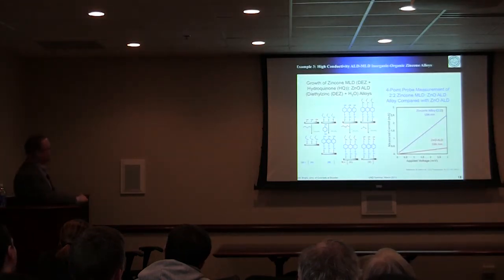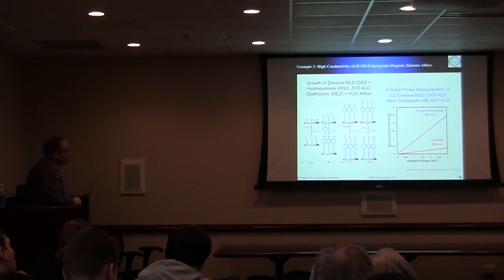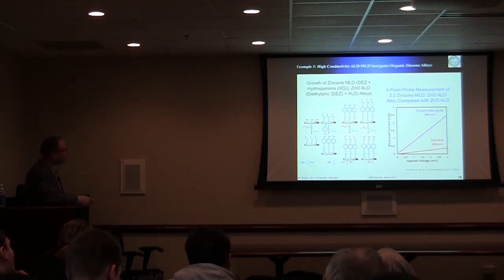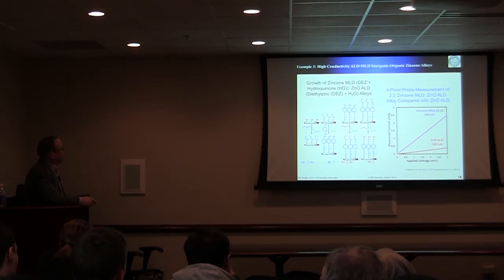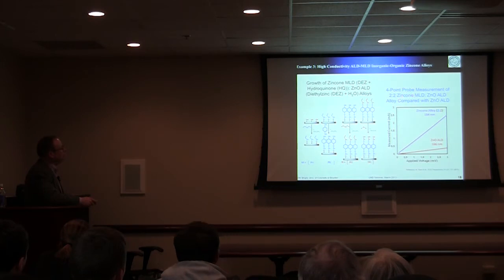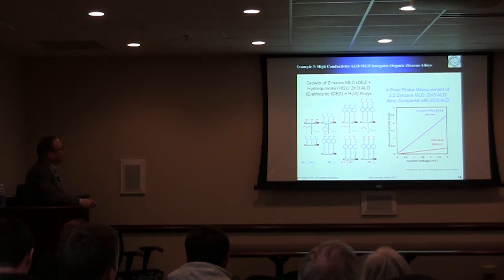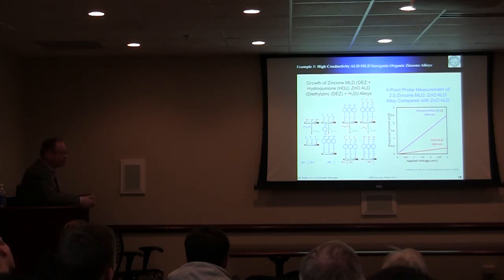And so, speaking of transparent interconnects, more recent work from CU Boulder would be zinc oxide or zinc-based MLD based on diethyl zinc. And with this type of material, instead of alucone, we could produce something called zincone. But once you mix zincone with zinc oxide ALD, depending on the ratio of the two, one can actually tune the electrical properties of the coating. It is a transparent coating. It's a flexible coating. And the idea behind this research is to find a replacement for ITO, for transparent electrodes.